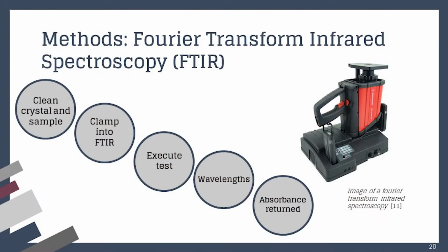The fourth test we used to characterize the composites was Fourier transform infrared spectroscopy, which is more easily known as FTIR. And this is a very precise machine. So before testing, we would clean the crystal that's in the machine, and for each sample we would wipe it down with ethanol to remove any residual oils from handling or any materials or dust that could be on the surface that would skew our results.